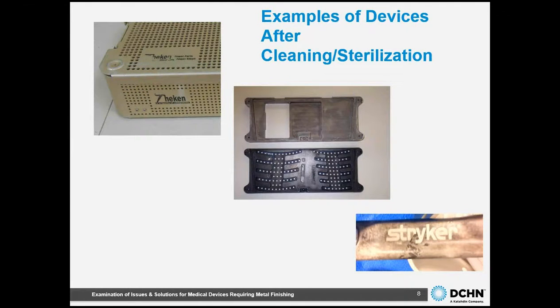To illustrate this point, here are a couple of photos of a tray, a module, and a device that have seen multiple cleanings and sterilizations. They don't have to look good. Well, they don't look that good, do they? Sorry about that. In many of these cases, the device had to be removed from service. And you can see there is significant degradation of the coating after it's been through these cleaning cycles.